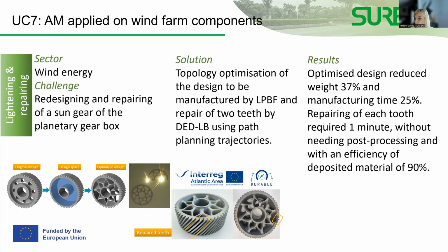The results were really good because we were able to reduce the weight of the part by 37%, and also the manufacturing time by 25%. And regarding the repairing, we were able to repair each tooth in 1 minute or even less than 1 minute without any need for post-processing, as it is, which is a huge advantage, and with an efficiency in the deposited material of 90%. So it's a very good result to demonstrate the possibility that additive manufacturing can make in this kind of components.